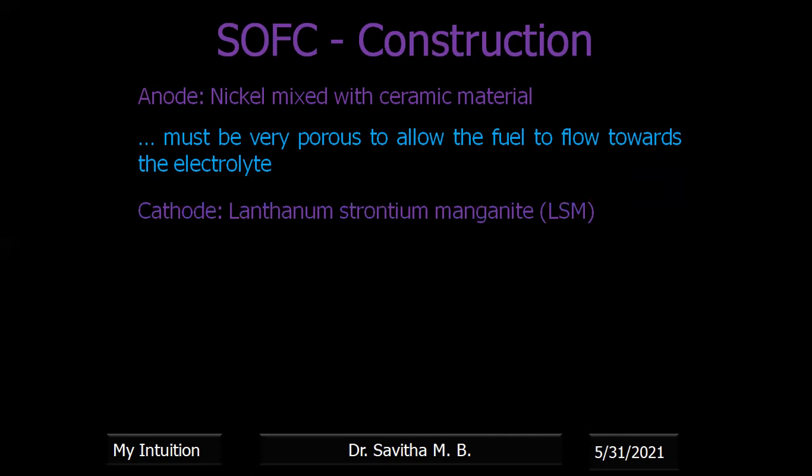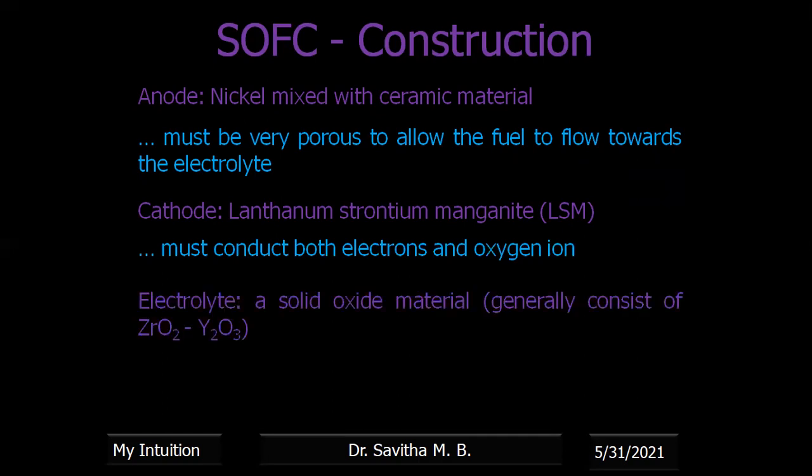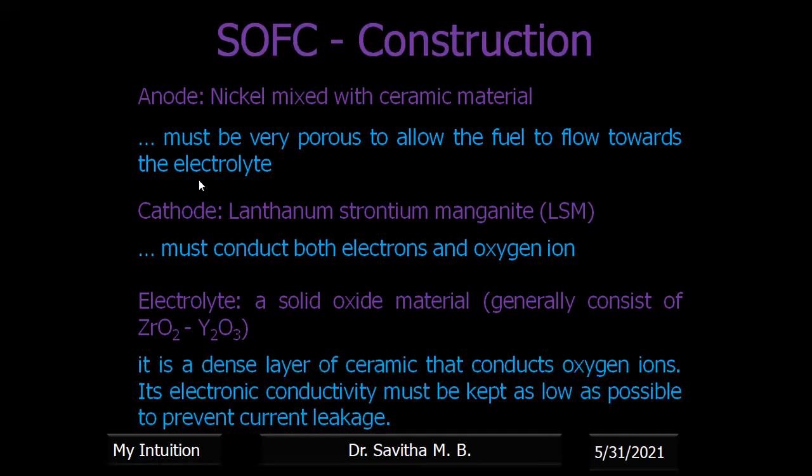Similarly, the cathode material taken in a solid oxide fuel cell is lanthanum strontium manganite, abbreviated as LSM, and it should conduct both electrons and oxide ions, that is oxygen ions. The electrolyte taken is a solid oxide material, generally zirconia yttria based. This electrolyte is a dense layer of ceramic which conducts oxygen. Like the ions conducted through an electrolyte, here there is a conduction of oxide ions,